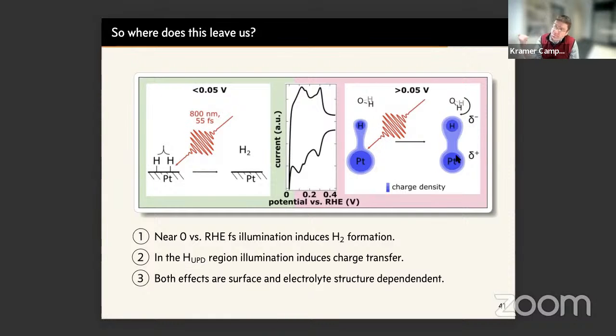There are ways to address this from an experimental setup perspective. In the typical pump-probe scheme, you take many photographs at many delay times. But of course, you don't need to do this, particularly if the kinetics that you're interested in extend to much slower timescales. You can do one pump pulse and follow it by several probing events. And so for more dilute systems, where the diffusion of reactants to the interface is slow, one would have to think about ways to overcome this problem. Sure.